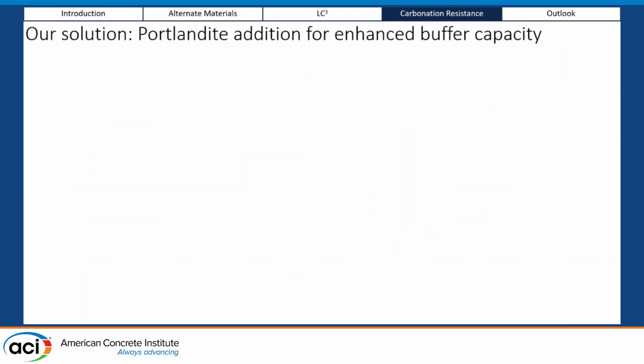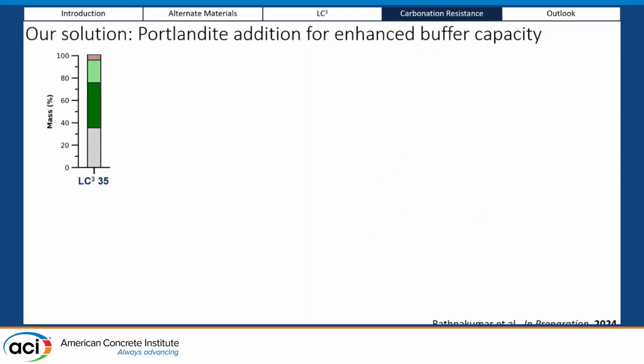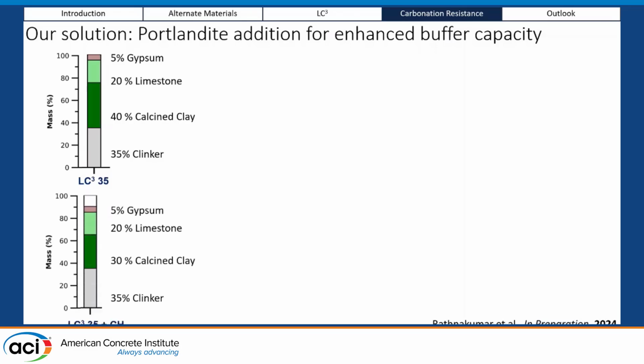Our solution to this problem is depicted in this slide. We add a certain amount of portlandite in the starting mix to enhance the buffer capacity of our low-clinker LC3. So this is a traditional LC3-35 blend with 35% clinker, and the rest is calcined clay, limestone, and gypsum. Our new blend is LC3-35 plus a little bit of portlandite, as given in this picture. So we have the same clinker content, but we are adding about 10% of portlandite in the starting mix.